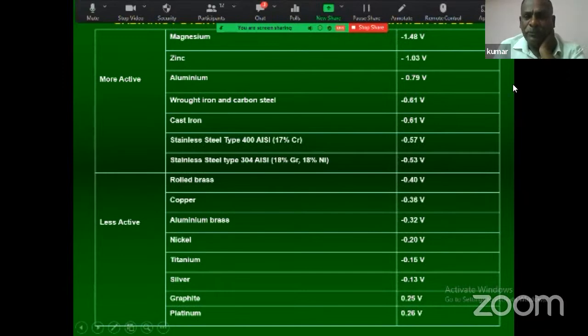Okay, so when you are talking about cathodic protection, we have to see the free energy of the materials. For example, generally we can classify materials as more active and less active. For example, platinum is less active. That is called a noble material. Platinum, silver, and gold are all noble materials. They will not corrode in the atmosphere. An active material, if you keep it outside, will start corroding. Magnesium is more active. Zinc, aluminium, iron, cast iron, stainless steel, and so on. So these materials are very active.